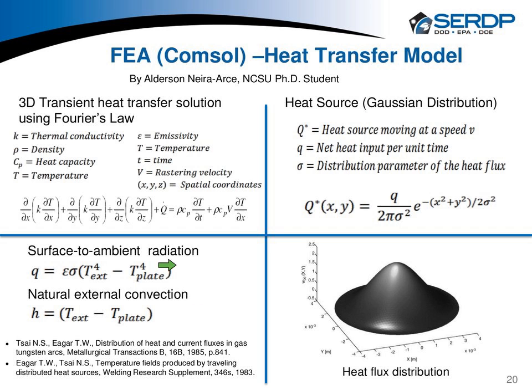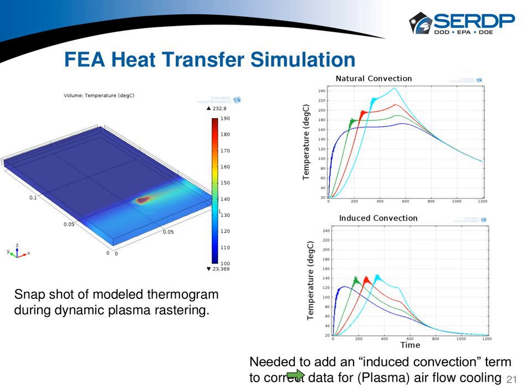I don't want to spend a lot of time on this slide because it's very complicated. But because this heat issue was so important, especially on the inside of the ship, and if we were going to use plasma around other types of operations or in inside enclosed spaces, we really had to understand heat input. We took advantage of another project that we had at the time, with electron beam melting for additive manufacturing. We had a graduate student who had developed, based on sound scientific principles, Fourier heat transfer law, the heat input as a function of various parameters. And using a Gaussian distribution, we modeled that with the example that I just showed you as one.